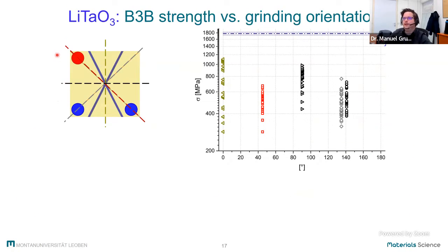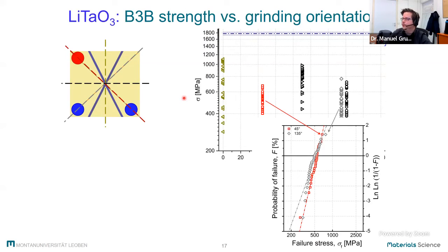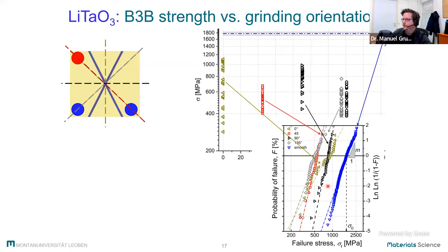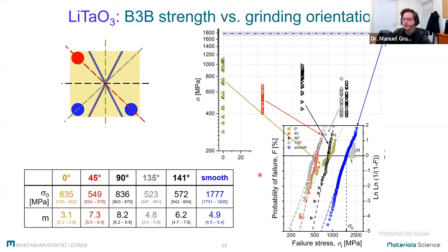So we moved on and selected specimens with all kinds of different grinding groove orientations on the surface. And what we could see was that we get the lowest strength values for grinding grooves parallel to the cleavage planes, better values for grinding grooves at an angle to the cleavage planes. And all of them are, as we expected, much lower compared to the mirror polished ones. If we have a closer look at the values, we can see that they can differ by 50%. So if we can tailor the grinding orientation, we can decrease the impact of those grinding grooves on our materials.